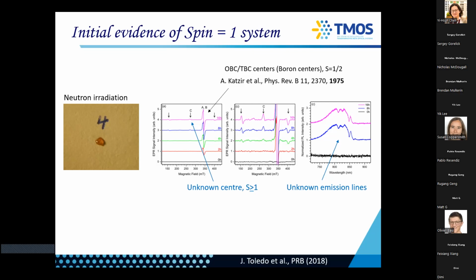Okay. However, if you keep irradiating, and to this date, we don't know why we kept irradiating, but we kept irradiating to 8 and 16 hours, you start seeing another signature, which is here and here. And so this line C is actually a spin, back then we thought bigger than 1, just because of the behavior of the EPR. You don't have the symmetrical peak. And when we took the sample back to UTS, we saw that this also has an emission around 800 nanometers.